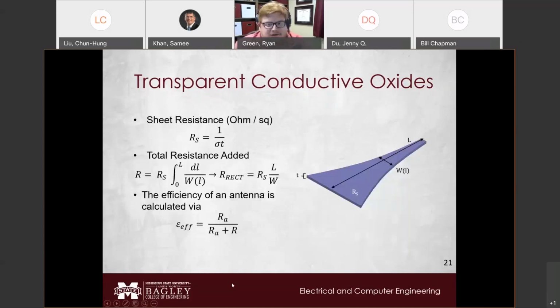Another thing to keep in mind is that because we are dealing with thin film antennas, we have this added resistance that comes because of that thin film. So we're adding in parasitic resistances that can be calculated through calculating our sheet resistance and then calculating our total resistance, which is based off of the design topology. So let's say that we have a rectangle here instead of this wedge shape. If we had a simple rectangle, it's sheet resistance times the length divided by the width of that rectangle.